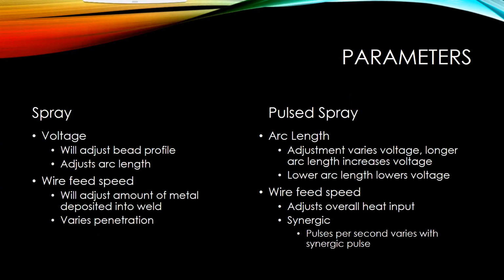So next I want to shift a little bit and talk about parameters used and how they vary between spray and pulse spray. When we're set up for spray, we're going to be adjusting mainly our voltage and our wire feed speed. Our voltage will adjust our bead profile, and it's also going to affect the arc length, arc length being the distance between the end of the wire and the molten puddle. Our wire feed speed is going to adjust the amount of metal that's going to be deposited, and it will also affect our penetration.